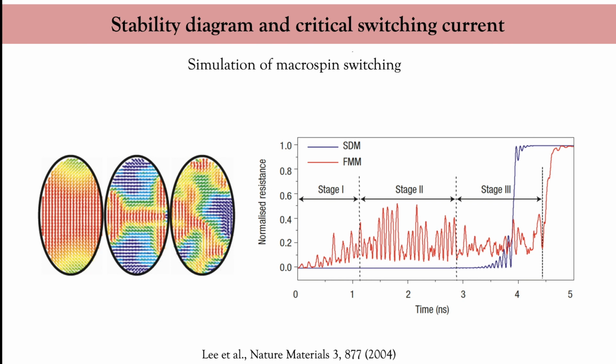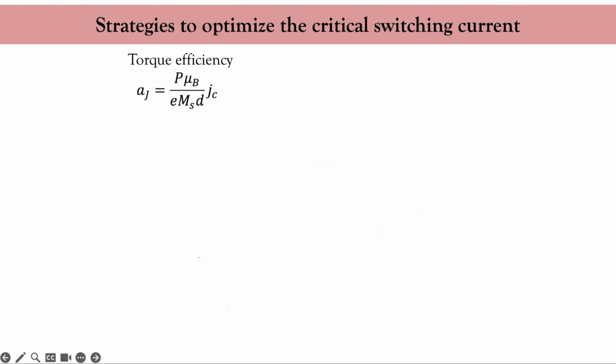Therefore, the magnetization switching occurs more likely via the nucleation and propagation of magnetic domains, such as the ones shown in the picture. Hence, the switching occurs via different states of excitations displaying large magnetic fluctuations during the reversal process. Spin transfer torque is a fantastic tool to control the magnetization of small magnets with a current. It has been investigated in a lot of different materials and different configurations in order to reduce the critical current required for magnetization reversal. What have we learned over the years?